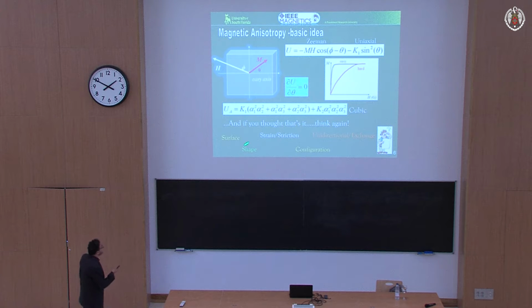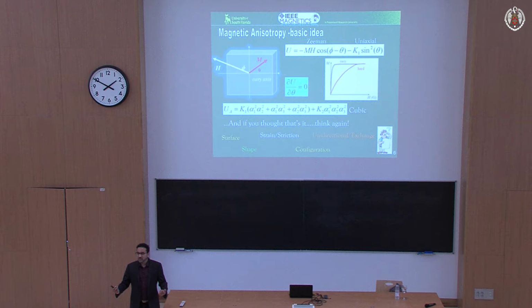Okay? And the next is shape anisotropy, and this is very easy to understand. You can make nanowires or nanorods. I talked to Lucas, and saw some of the work that they're doing on nanowires. In this case, you have a preferred direction, and the magnetization prefers to lie along the longitudinal axis. So you can change the shape of the particles and make sure that you are controlling the anisotropy, and that helps you for certain applications. Strain can play a role.